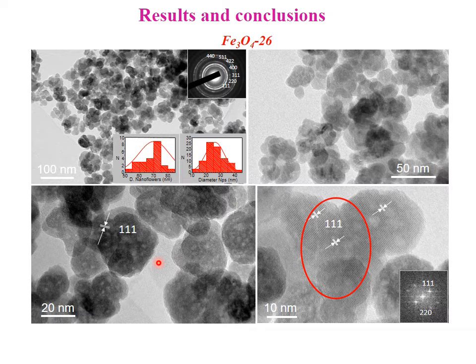The magnetite flower-shaped assembly of 70 nanometers, formed by 26 nanometer nanoparticles, has also been prepared. In both cases, the individual crystals forming the nanoflower and nanocluster are attached in a common crystallographic orientation, as observed in the high-resolution microscopy image.